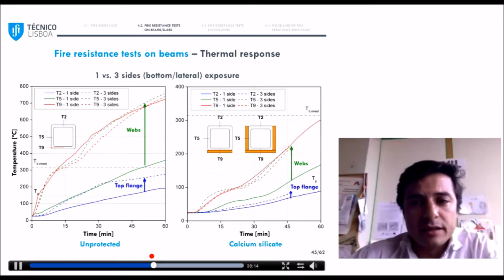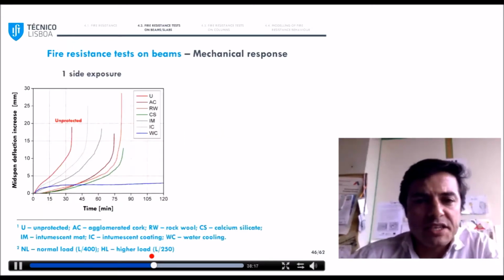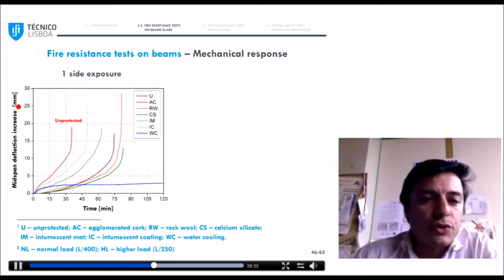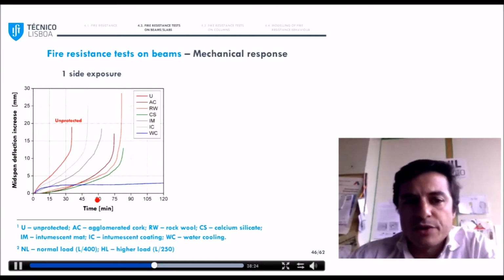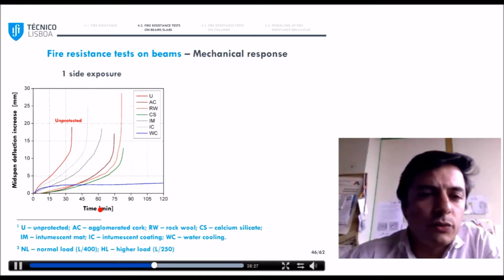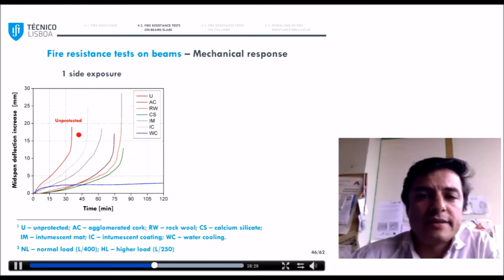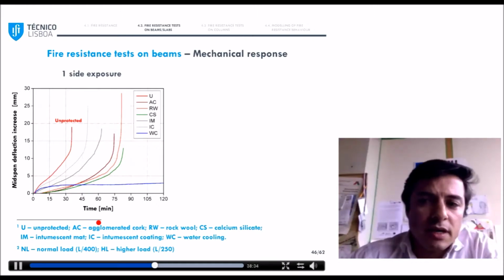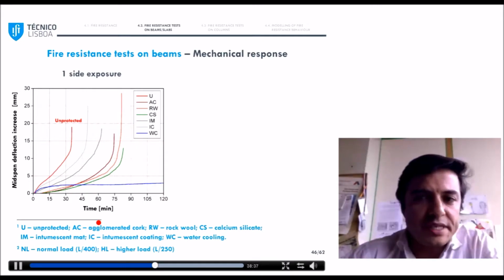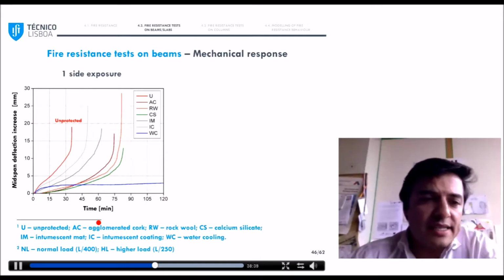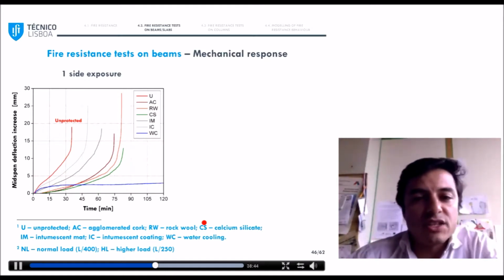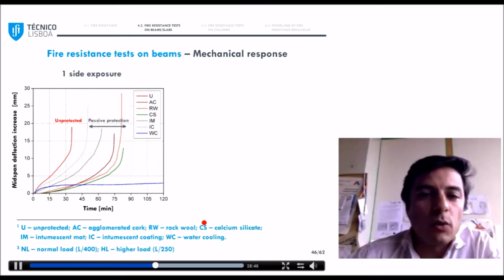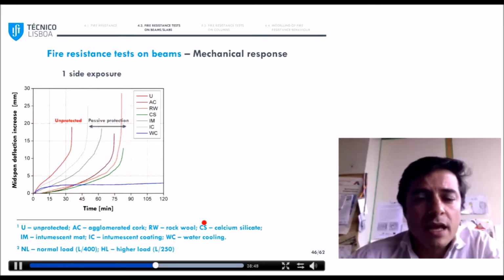So in terms of mechanical response, we can see here in this slide a picture with mid-span deflection increase as a function of time for the different beams. I will help you out with the different curves. So in red, for 1-side exposure, we can see that the unprotected beam suffered a rapid deformation increase. This was due to the temperature rise and the consequent loss of stiffness, first in the bottom flange and then progressively in the webs and top flange.